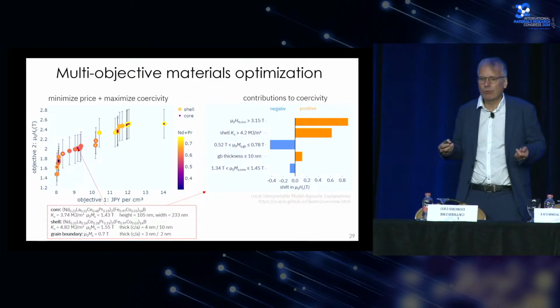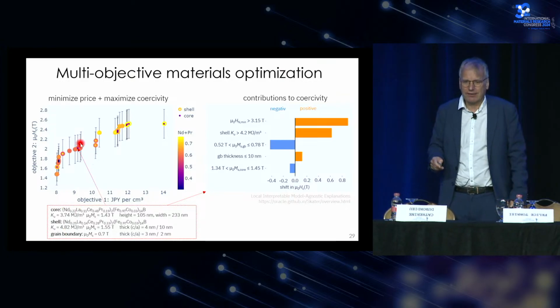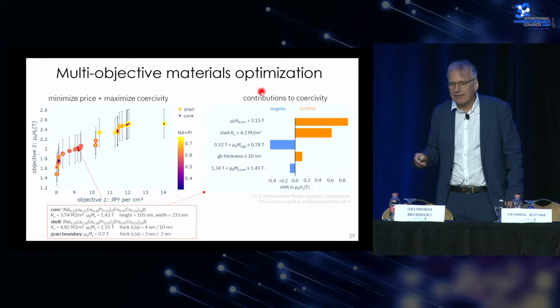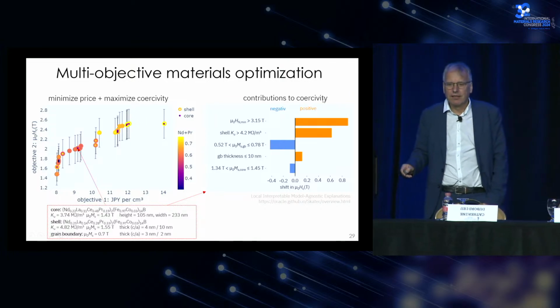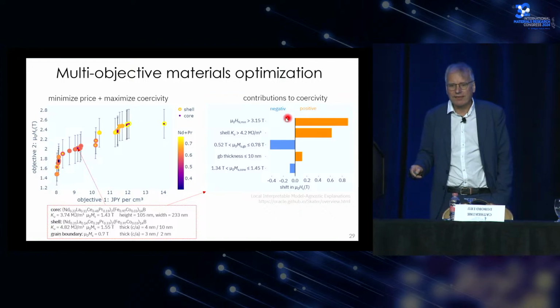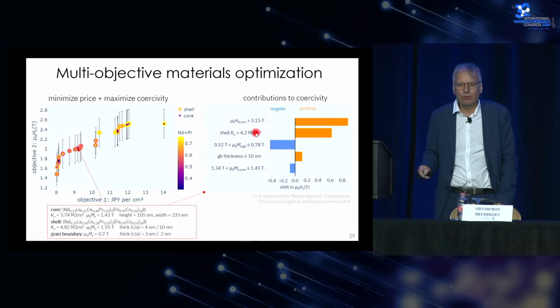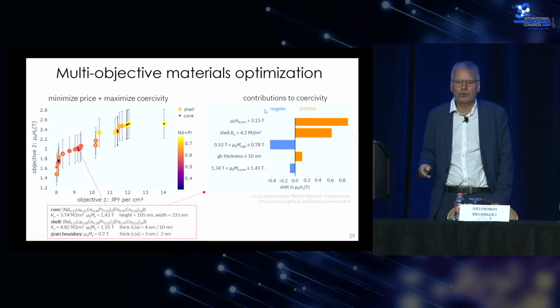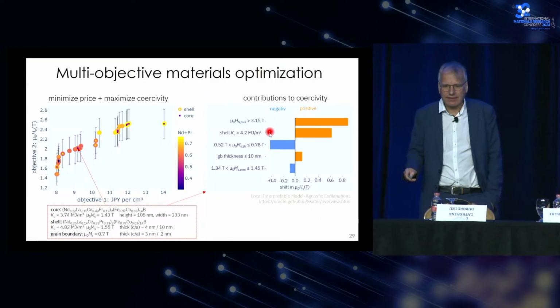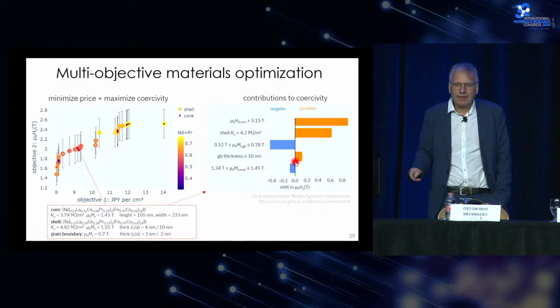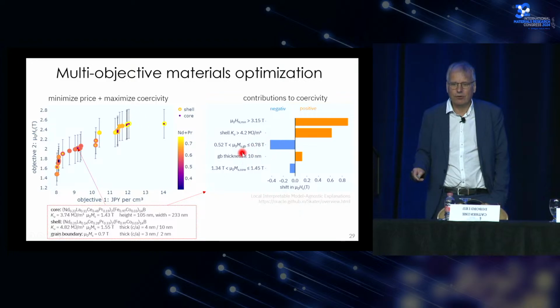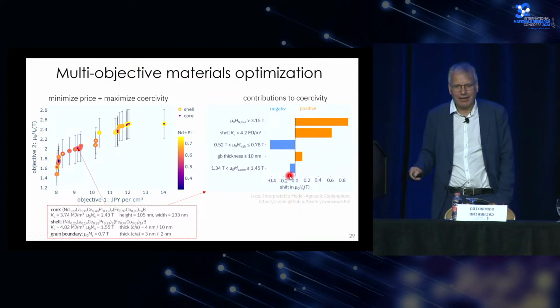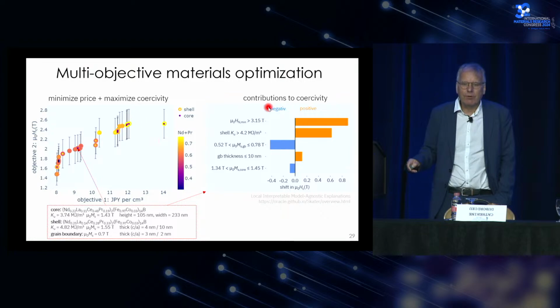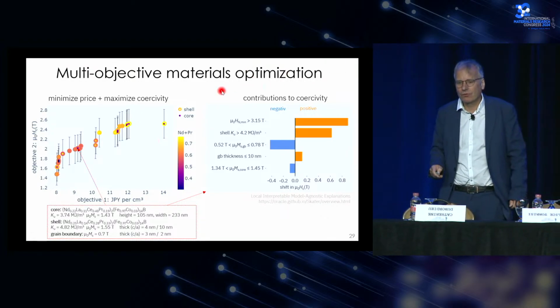Again, we can use the machine learning model to tell us a little bit on why this magnet here has a certain coercive field. So we can look at the different contributions to the coercive field. So a very positive contribution is that the intrinsic average switching field of the two phases is very high. A positive contribution is that the magnetocrystalline anisotropy of the shell is very high. We have a negative contribution. We assumed, as it occurs in real magnets, that there is a soft magnetic grain boundary phase. It's positive that this grain boundary phase is smaller than ten nanometers, and it's negative that it has a high magnetization. But for each of these points here, we can see what are the different factors that contribute to the coercive field of the magnet.